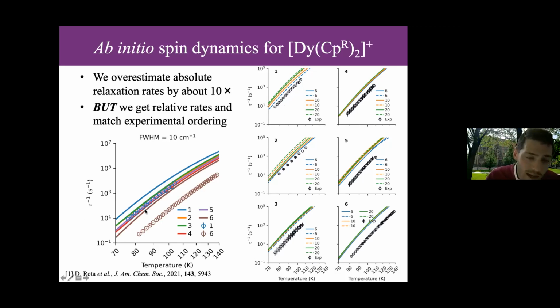But the most important thing for me is that we get the experimental ordering right. We always find in this range of line widths that compound 1 is the fastest and 6 is the slowest, and that 2 to 5 are very similar to each other. And so this tells us that whilst we're overestimating absolutely, the relative quantitative rates are accurate for our compounds, that is, we are discriminating the differences between them accurately with ab initio calculations. And so to me, that's a really nice thing, which means we can believe these results in some way and try and understand what they're telling us in terms of the chemistry.